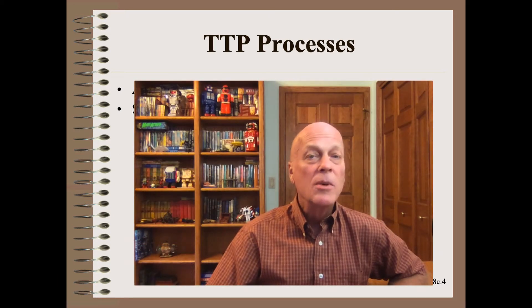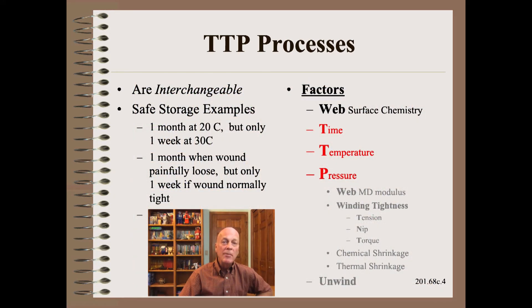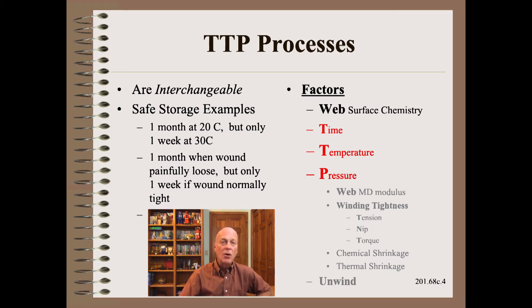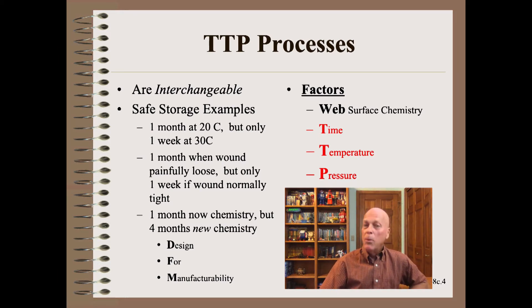Example two requires knowing a bit about winding tightness, which we will outline here but is covered in great detail in the award-winning web 101 class. The outcome is that pressure comes from winding physics — that is, you may be able to store safely for a month if you wind painfully loose, but only one week if you wind normally tight.